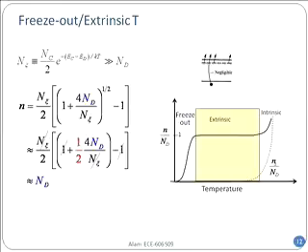But you can see, as you raise the temperature, n sub xi will get larger, and as it gets larger, you'll be able to make this expansion, and then that will equal n sub d. What happens at lower temperature? n sub xi will be a smaller number. If it is a smaller number, you will not be able to make that expansion, and when you cannot make that expansion, you will see the carrier concentration going to 0. So this is something you should check out.